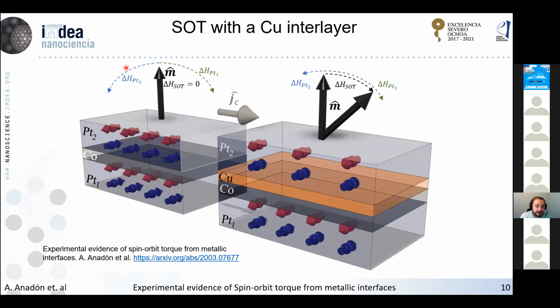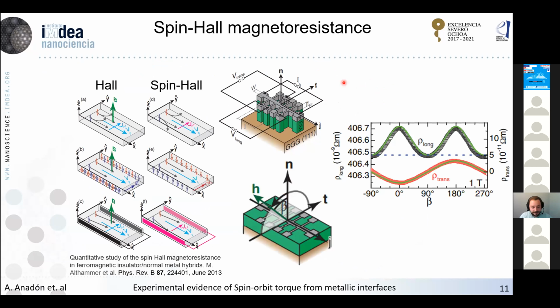Basically, the picture that we observe here is if you go to the symmetric system, then you have two contributions that compensate each other, and then you don't have a net spin orbit torque. While in the case of the copper interlayer, you have one of the contributions which is larger than the other, and this gives rise to a net spin-orbit torque. So now, to understand the origin of this difference in the spin-orbit torque, we are going to use the spin-Hall magnetoresistance effect. And luckily, we had Saul before me that gave a very nice introduction about what the spin-Hall magnetoresistance is.